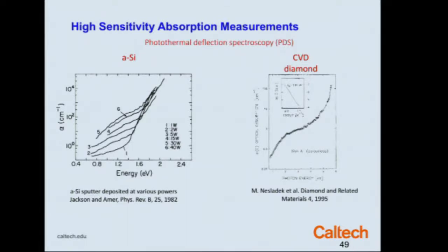So I won't go into this in detail. We have methods that were developed first at Lawrence Berkeley Labs and used actually to characterize the mirrors for the LIGO Michelson interferometer, called photothermal deflection and photoacoustic spectroscopy. They basically measure a temperature-induced refractive index, and they can make measurements of refractive index that are a couple of orders of magnitude more sensitive than we can by ellipsometry or conventional transmission measurements.